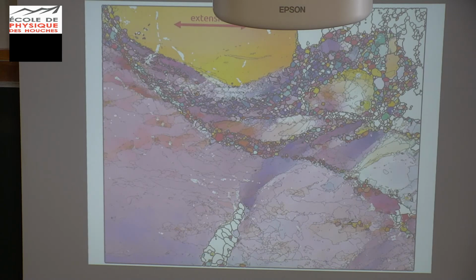Now we just see this kind of subgrains that run parallel to C, but you can see that they are not the most common one. The most common ones run parallel to 101. They are very regular and form these subgrain cells. So we are going to focus now on these ones, and more specifically here, where we can see this zigzag configuration and full loops.